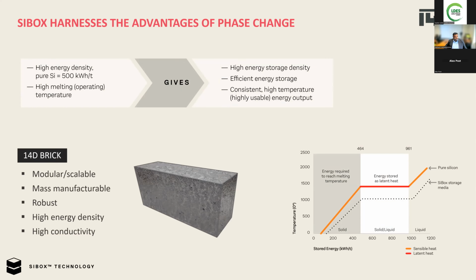Now, the metal that we use is a silicon-based alloy. Silicon has one of the highest energy densities in terms of its latent capacity, right? The only other element you would think of is boron, but using boron is very, very hard in this context. So what we've done is we've added some herbs and spices to the pure silicon, and that's what the Sibox storage media looks like in terms of its energy storage profile. This plot is inverted compared to what Alex had shown earlier. So you can see the latent band over here, which extends over a fairly large energy landscape.